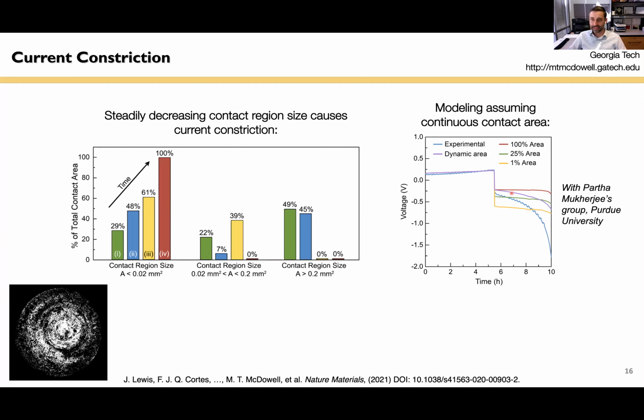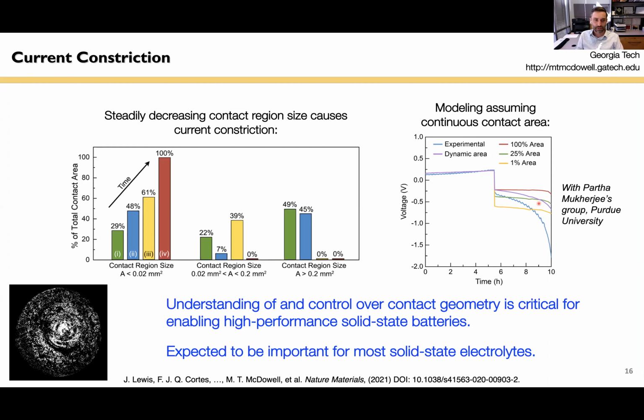And so what we found is we can't, because we weren't taking into account these isolated contacting points. And so we have a much steeper increase in overpotential than we would expect based on just the overall area of contact. And so the moral of the story here is that it's the formation of these isolated contacting points which is really important and which really drives the failure of our cell. This increase in overpotential corresponds to failure. And this is happening because when you're forcing currents to go through these very small contacting points, you exhibit this larger constriction resistance. It's constricted current, and there's a much larger resistance around the edges. And so this is what drives this increasing polarization of the cell.